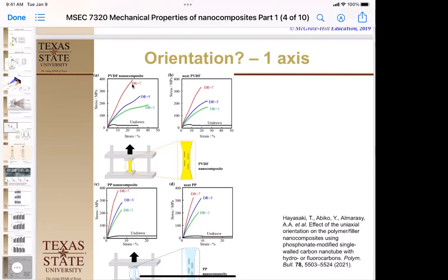Now, most films don't necessarily have to have a draw strength on them, but a lot of them do. They actually are drawn out during the process, and that increases their strength. But synthetic fibers almost always have to be drawn out 10, 50, 100 times their initial length, because once you draw your fibers out like that, they are just super crystalline. You said that you have to draw them out twice the length, right? It depends. Here they did 3, 5, and 7 times. So it depends upon the length of the fiber that we're beginning with.